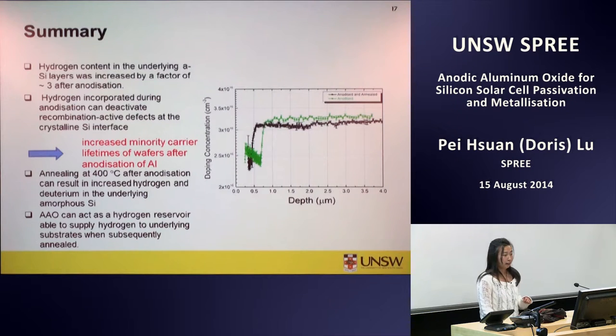We further did this analysis on a commercial wafer with only 10 nanometer of thin silicon dioxide passivating the surface, and anodized a layer of aluminium on top. We stripped off the anodic aluminium oxide and silicon dioxide to detect the boron concentration within the wafer. We can see that after anodization, the first 0.7 micron of boron is deactivated at the interface. And after anneal, the hydrogen is redistributed deeper into the wafer, more than 2 microns. As we can see, the boron concentration slowly comes up to the background doping level as the sputtering time increases.